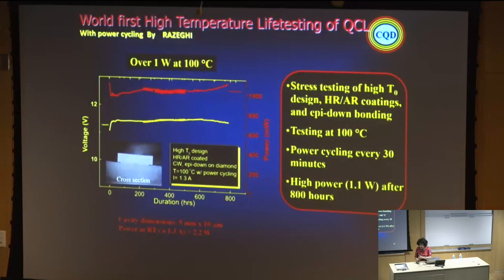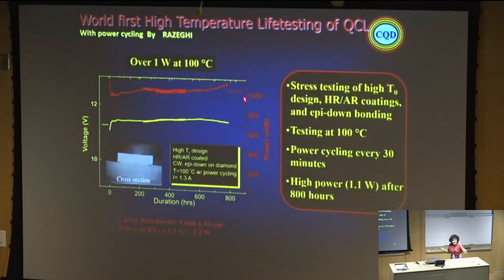So again, I want to say that the result I'm showing you is not only one publication, you have to know that. We did stress testing of one of the structures that we developed for high T0, at 100 degrees C, with power cycling every 30 minutes, with more than 1.1 watt on the sample, with AR coating, HR coating, epi-side down, all of the different technology, and demonstrated more than 800 hours and more, with no change. It means that everything I'm explaining to you, especially in indium phosphide, this kind of laser, once you control all of the defects, is forever.